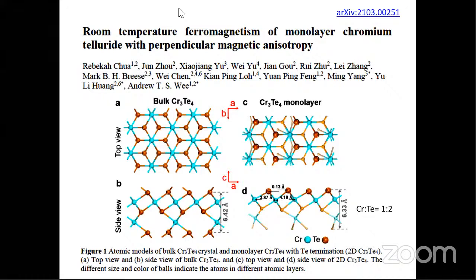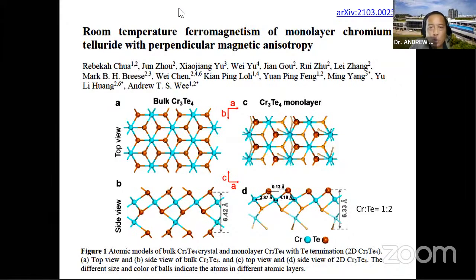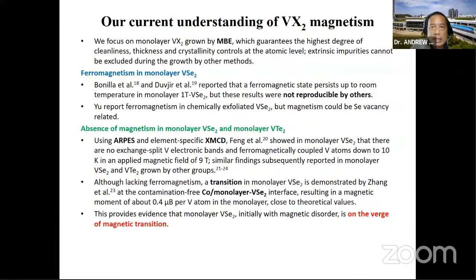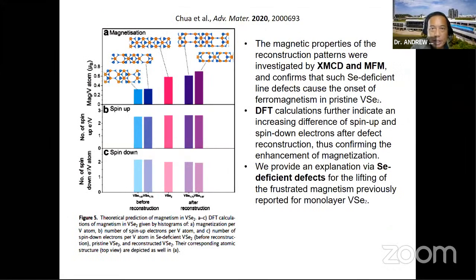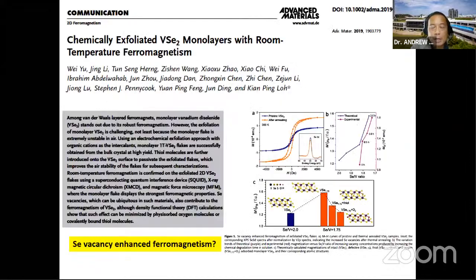So during the chemical exfoliation, is there any increase in the temperature, Professor? Okay, the chemical exfoliation experiment was not done by us. As I mentioned to you, it was done by our colleague in the chemistry department, KP Low. So I do not know whether there was any increase in temperature. There could have been, but the key point is that when you do chemical exfoliation, you cannot avoid introducing some external elements into your sample, and hence we think that the magnetism measured is extrinsic. But if you want to know details, please look at this Advanced Materials paper.